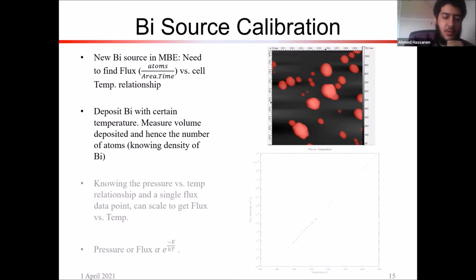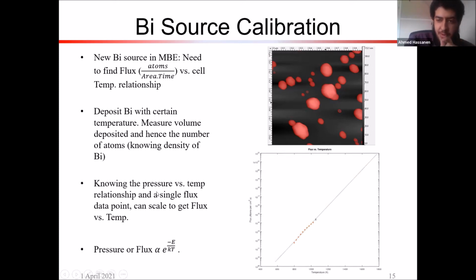And so knowing the pressure versus temperature relationship and this data point, the single flux data point between temperature and the atoms deposited, we can start to get a picture or a calibration for what temperature to apply in order to get the flux we want. So we've calibrated the bismuth source.